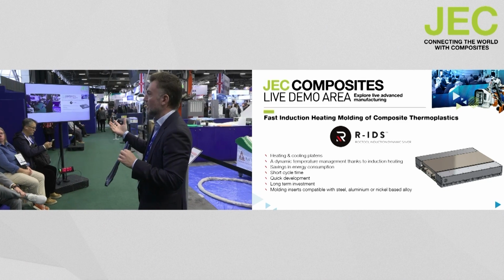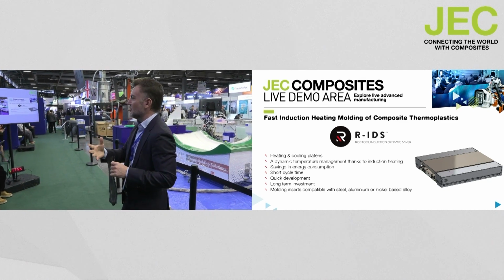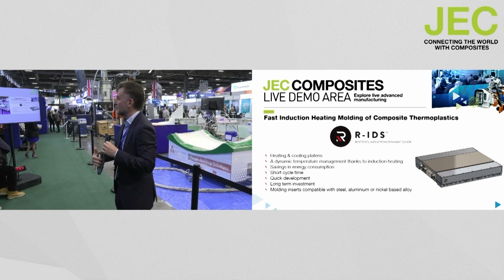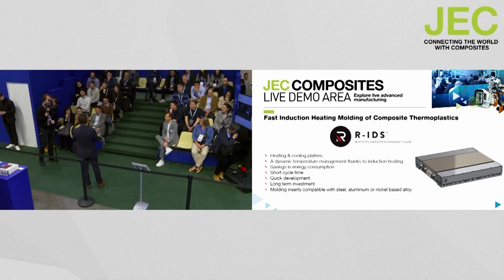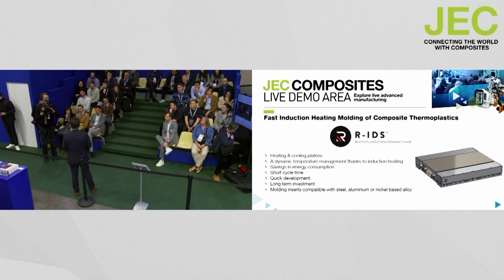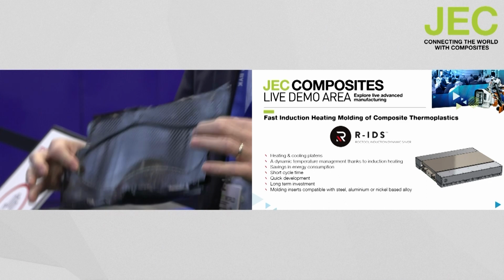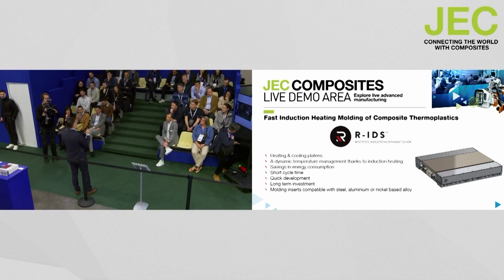If you try to do that where you preheat materials and transfer them very fast to a cold mold, it's quite difficult to get to that level of quality and that level of resin-rich surface directly from a pre-preg. So that part, in terms of cycle time here at the show, is 5 to 6 minutes using a heat platen. Because Roctool is known also for the same technology integrated in molds, but here it gives you the ability to change molds and to change inserts as you need.